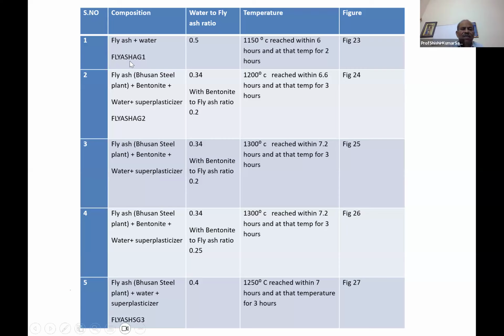The first one is fly ash plus water, temperature 1150 we have tried. Then fly ash plus bentonite. This one with an admixture, fly ash with water. Then these are all with bentonite, fly ash with a superplasticizer, with bentonite, fly ash ratio, 1300, 1250 gives actually our optimum. Fly ash, Bhushan steel plant plus water plus superplasticizer, water to fly ash ratio 0.4, and 1250 degrees centigrade reached within 7 hours, and at 1250 it remains for 3 hours. This is the temperature.